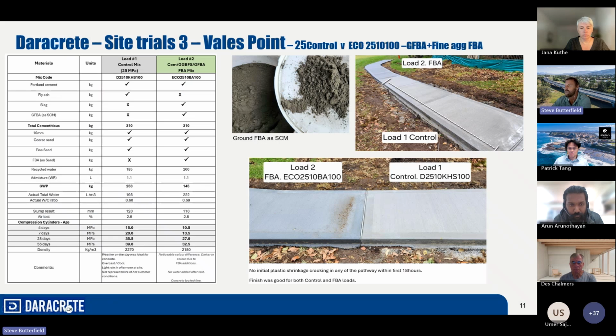Site trials 3 are obviously the ones that have been discussed here. That's usually the Vales Point material. Again, here we had the control mix, which the guys have gone through, which is basically a standard 25 MPa 100 slump. That was in one part of the footpath, and the other part of the footpath had the tri-blend of GP, slag, and ground furnace bottom ash as a cement replacement, and we also had the furnace bottom ash as a sand replacement in that mix also.